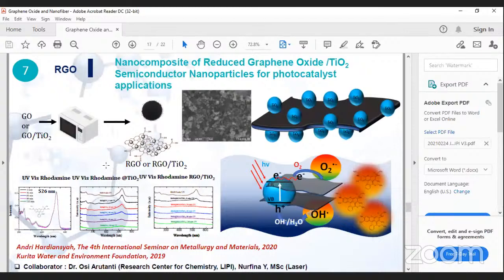And in the second section, we try to use the ferro-oxide and then gold nanoparticles. And then here we use titanium dioxide in anatase phase in order to make some photocatalyst effect on our nanocomposite. And it works as a photocatalyst, and we use rhodamine as a model for the pollutants.